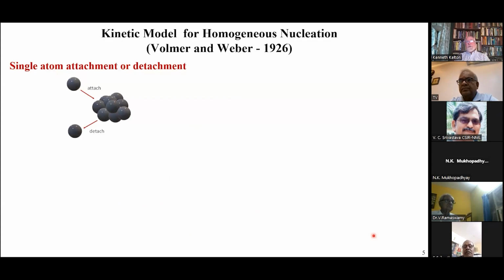The kinetic model of nucleation came later. Gibbs was the late 1800s, Volmer and Weber were the early 1920s. What they said was that you have clusters growing kinetically by either a single atom attaching from the vapor phase or that atom detaching from the cluster. The fact that they can attach and detach illustrates the stochastic randomness that is inherent in nucleation processes, as opposed to growth processes.